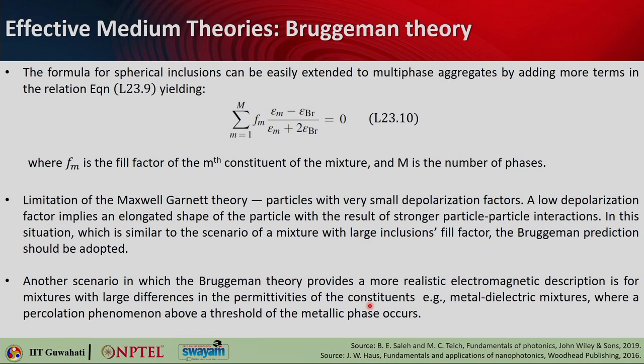Another situation in which Bruggeman's theory looks more realistic is for mixtures with a large difference in the permittivities of the constituents, such as metal-dielectric mixtures, where percolation phenomena above a threshold of the metallic phase takes place. Above this critical metal filling factor, long connectivity forms between metal grains and the optical response of the mixture changes abruptly. In those cases, you should use Bruggeman's theory.